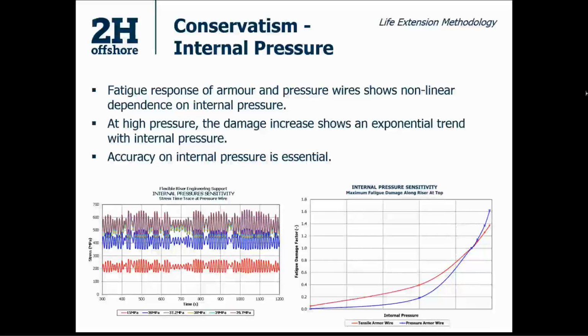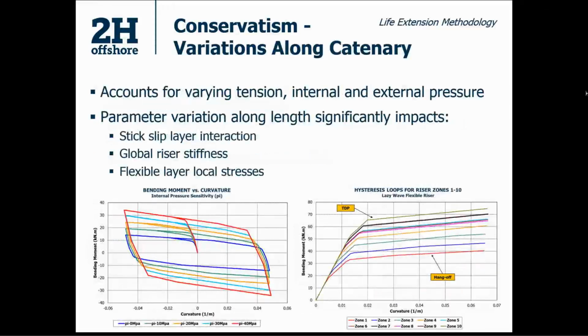And then taking that one step further, taking into account the variations along the catenary. So we know that tension, internal and external pressure are going to change, especially for a deep water riser. External pressure is going to vary quite significantly from the top to the bottom, but the internal pressure as well, for the same reasons that the fluid column will have an impact on the pressures at the top versus the bottom.